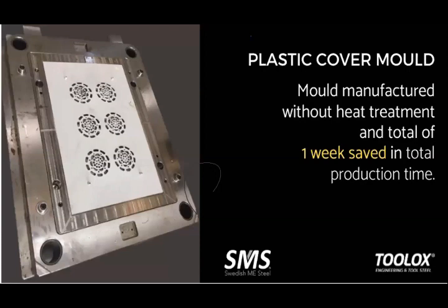This is a plastic cover mold which is manufactured in India. The previous material had started in ESR grade material. With Toolox 44, there was no heat treatment involved. Directly at 45 HRC, they had manufactured. Right after manufacturing, the customer commented that they were able to manufacture very quickly, with a saving time of more than a week. That's the saving that the metal can give to you.